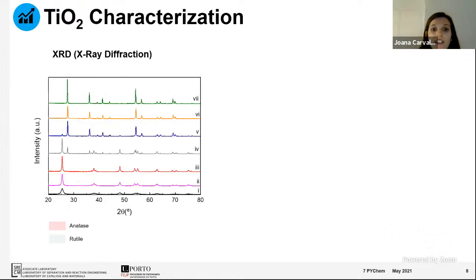Moreover, to define the phase transition of titanium dioxide, X-ray diffraction was done. In this graph are the diffraction peaks of the anatase and rutile phases, and the black line presents the material calcined at 400 degrees, followed by higher temperatures. This peak is representative of the anatase phase, and you can see that the peak is bigger at the lowest temperature. The same happens here, and in the case of rutile, the contrary happens. The material calcined at the highest temperature presents a higher peak.